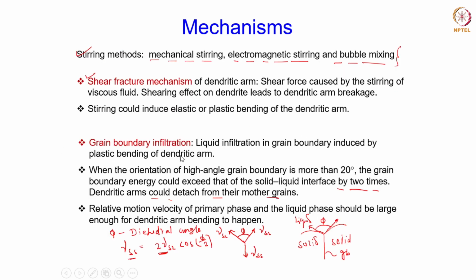Then we also talked about grain boundary infiltration, which occurs due to the plastic bending of the dendritic arm, again caused by the shear. When the misorientation across the grain boundaries due to this plastic bending exceeds 20 degrees, then the liquid penetrates the grain boundaries and leads to detachment of the dendrite arms from the mother grains. So this again produces more dendrites or grains and leads to grain multiplication, and as a result the grain size will be refined when the melt is solidified.